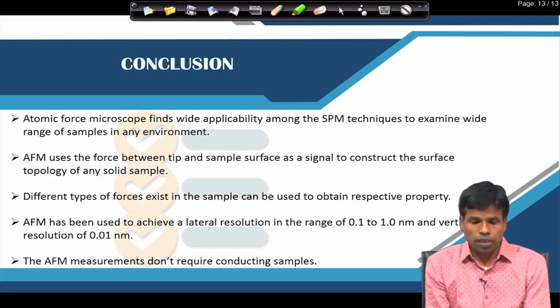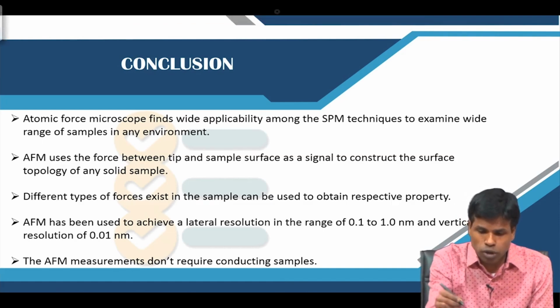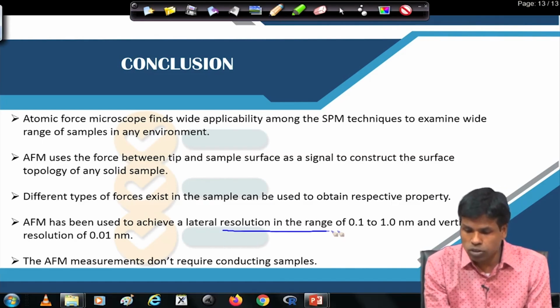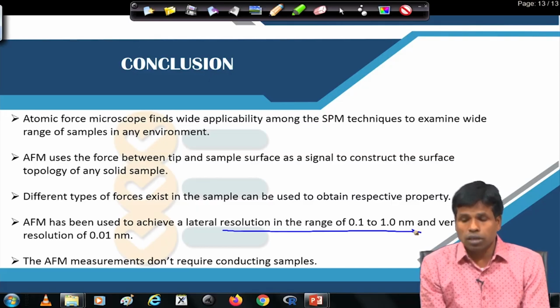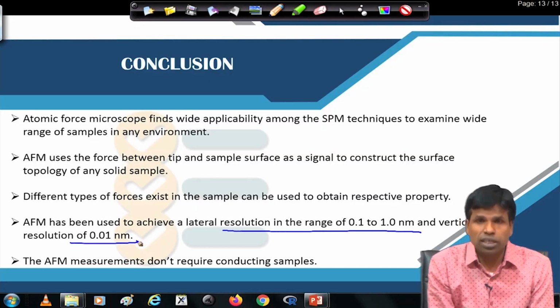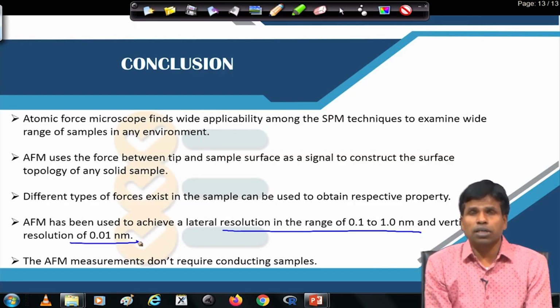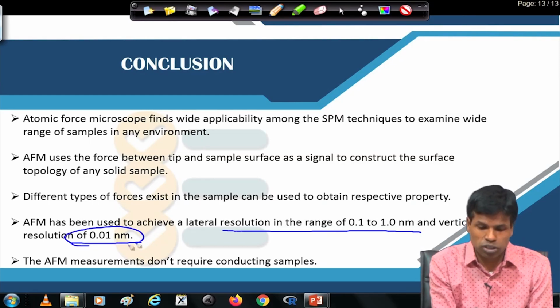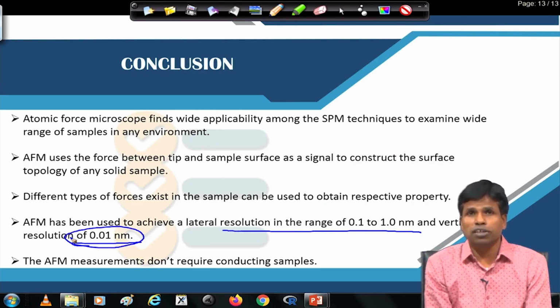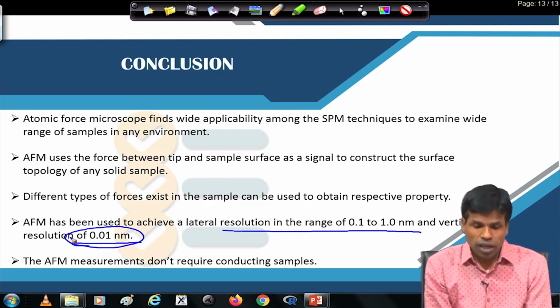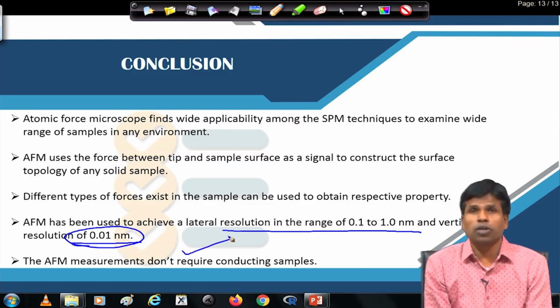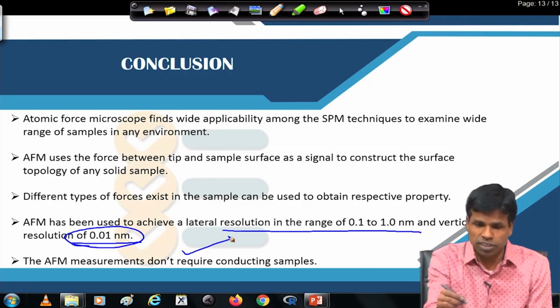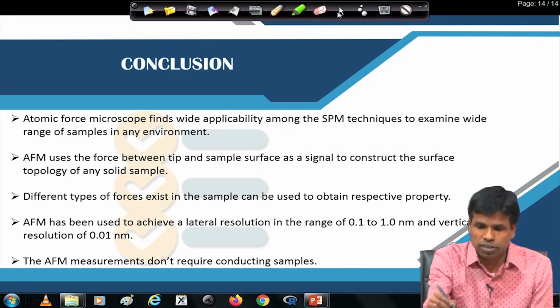AFM has been used to achieve a lateral resolution less than 1 nanometer and vertical resolution less than 0.01 nanometer, very high super resolution in the vertical direction. There is no other technique that can provide such a high vertical resolution. And for the AFM measurements, we do not require a conducting sample. All kinds of samples can be done, one of the major advantages of atomic force microscope.